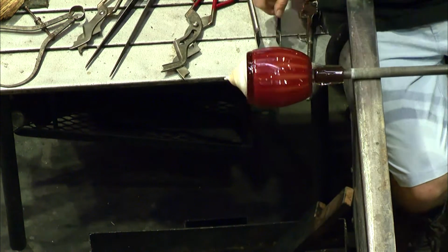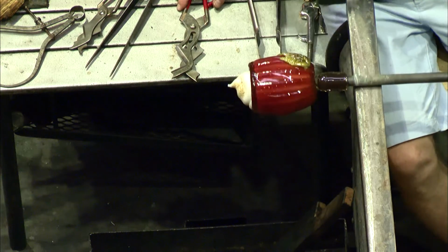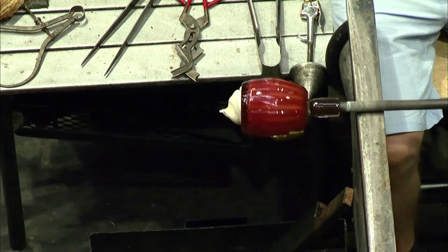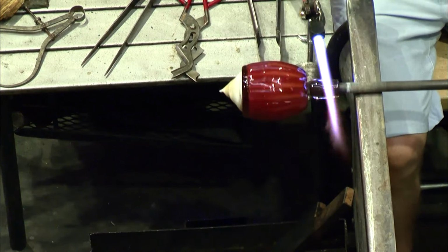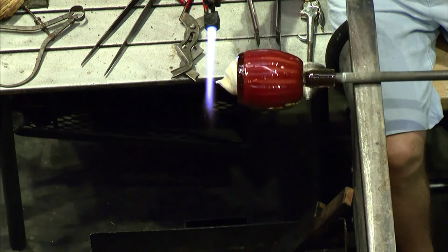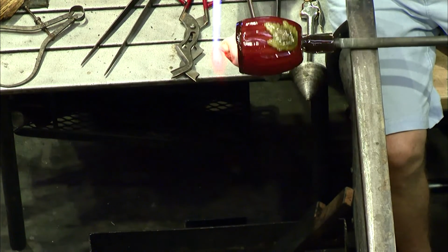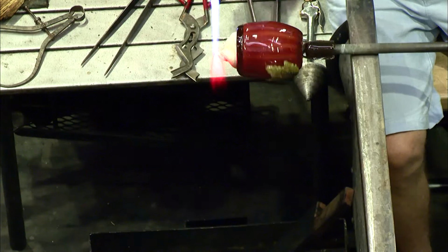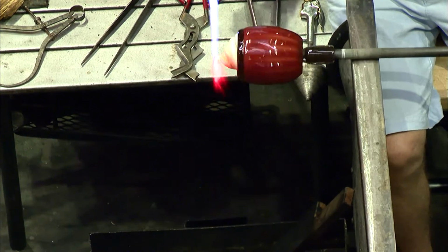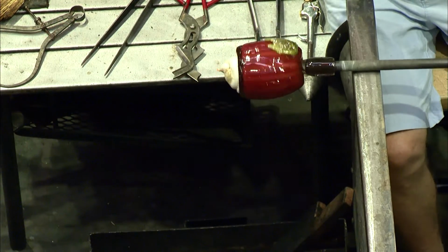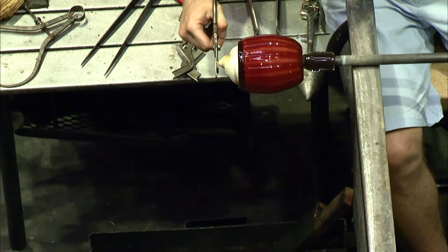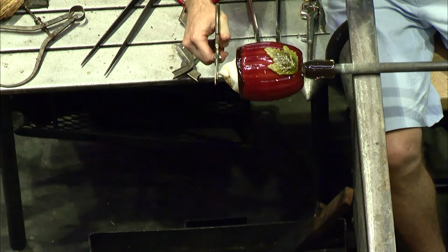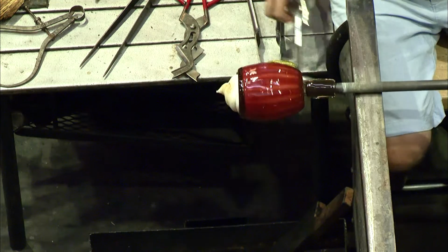There are circumstances where the glass will stick to the mold, that being a production setting. If we were making glass pumpkins, this particular team of 3 would probably be plopping a bubble down into those optic molds every couple of minutes, and therefore it's going to absorb some of that heat every time we put a bubble in it. And so eventually someone's going to put a bubble in it and try to take it out, and they're going to bring the mold with them.